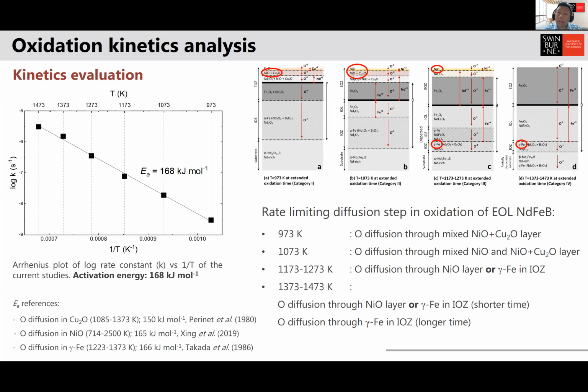And we think that, for example, at 973, the rate limiting step is oxygen diffusion in the mixed layer of nickel oxide and copper oxide layer. Thus, the effect of coating is quite significant in here. At 1073, we still thought that this layer is also affecting the process, and it's controlled by oxygen diffusion through this coating layer.